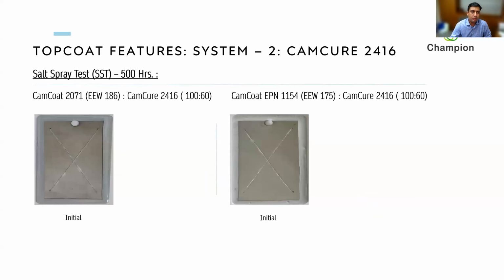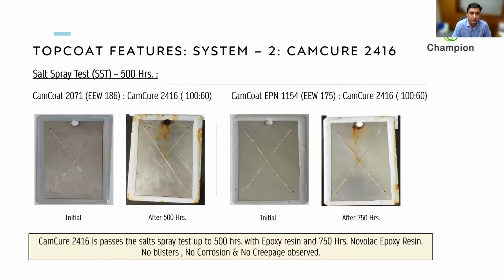We have also done salt spray tests. Similar to the previous slide, we've checked it both with basic liquid resin and with a Novolac resin. Camcoat EPN 1154 is a Novolac resin, and I'll talk a bit about that resin in a later part of the presentation. You will notice that the first one, with basic liquid resin, we checked after 500 hours, and with the Novolac resin, we checked after 750 hours. In both cases, there are no blisters, no corrosion, and no creepage observed. So this is a very good system for good all-round chemical resistance.